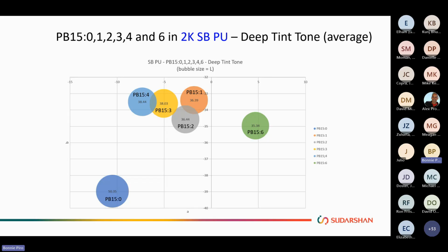The other alpha there, the 15-0, is unique in that in this particular formulation, it doesn't disperse as well. So we're not getting as much from a color perspective as you would see in other formulations. In other formulations, you would see that all the way over to the red side as well. So not all color indexes are appropriate for all formulations.